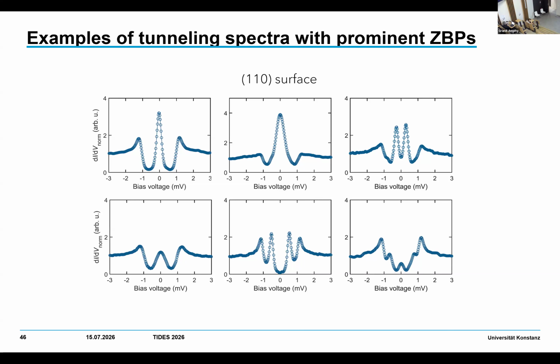Short question, how do you select all your orientations, because you have many different facets? As I said, we got two crystals from our collaborators which had surfaces. We were first using simply the crystals as we had them. We did some argon milling to clean, but then we took the surfaces that we had. We already had a conjecture of what the symmetry could be, and we were choosing directions which could be decisive and give us different cuts through this order parameter symmetry. And then also you see how we did it, right?